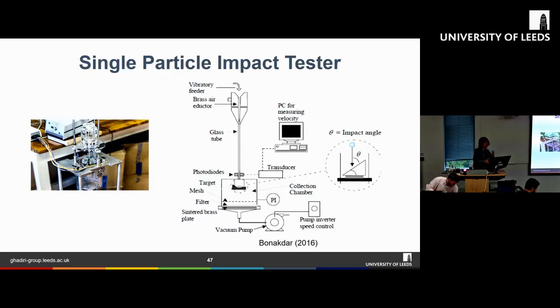Right. So we talk about characterizing particle impact breakage, and the tool that we use is what we call the single particle impact tester, as you can see in the picture on the left, which is a device we have in LIT, an in-house built device. So here is a schematic. Basically, how it works is that you apply a vacuum pump from the bottom, and then we feed particles from the top, and as a result of the vacuum created inside this chamber, the particle gets sucked down, accelerated, and impacts on the target, which is a very rigid target made of sapphire glass. And as a result of that impact, the particle breaks.